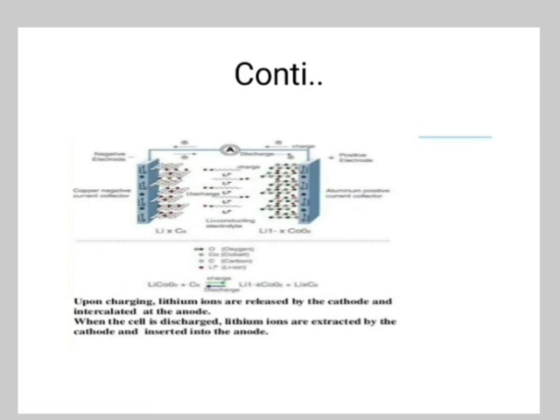There are significant differences in energy when comparing lithium-ion and lithium iron phosphate. Lithium-ion has a higher energy density at 150–200 Wh/kg versus lithium iron phosphate at 90–120 Wh/kg. Lithium-ion is normally the go-to source for power electronics that drain batteries at a higher rate. On the other hand, the discharge rate of lithium iron phosphate outmatches lithium-ion at 25C. Lithium-ion phosphate batteries have excellent voltage discharge at higher temperatures, and the discharge rate does not significantly degrade the battery as capacity is reduced.